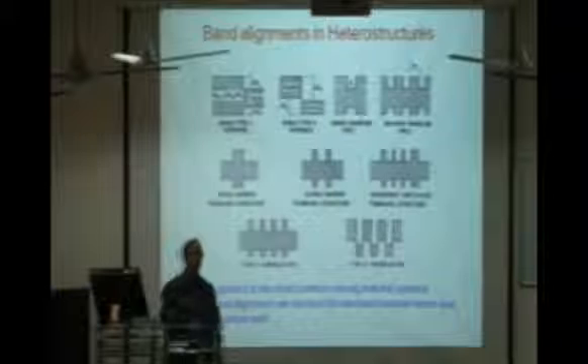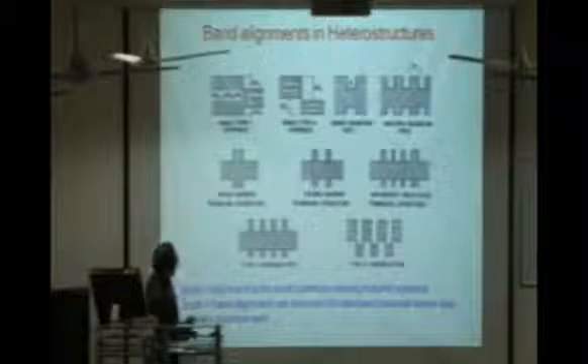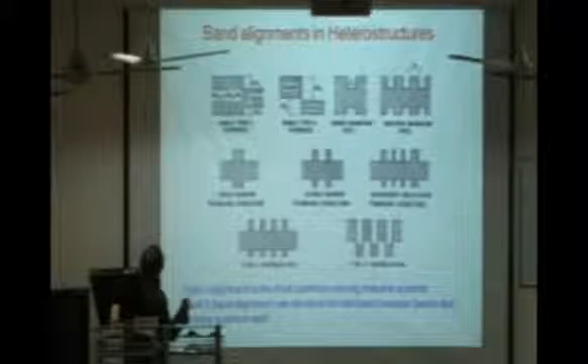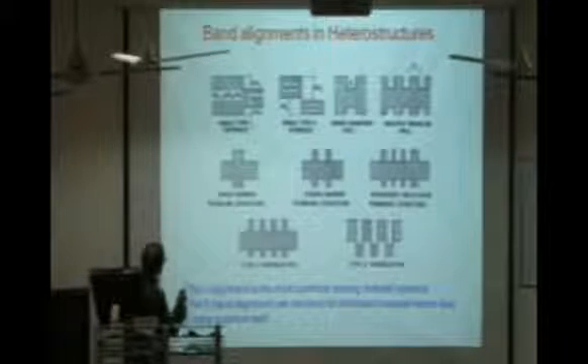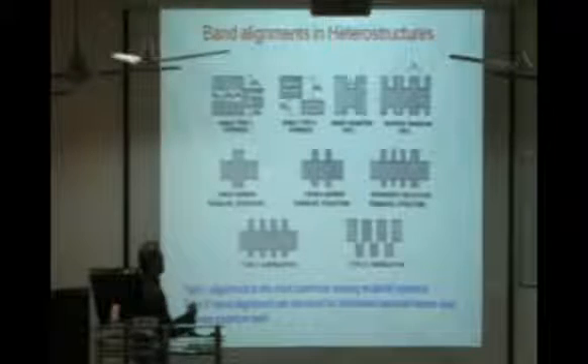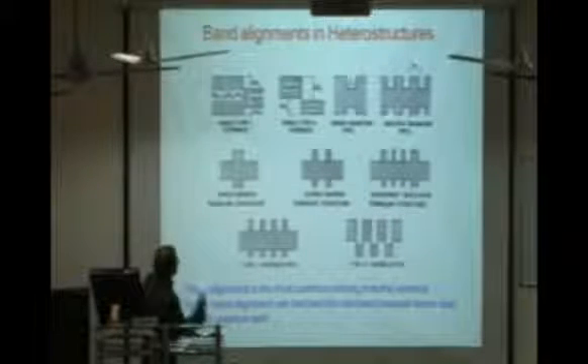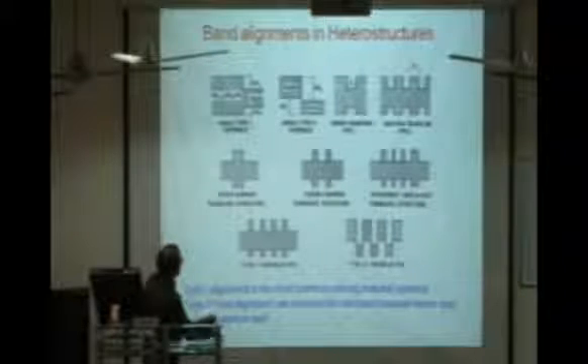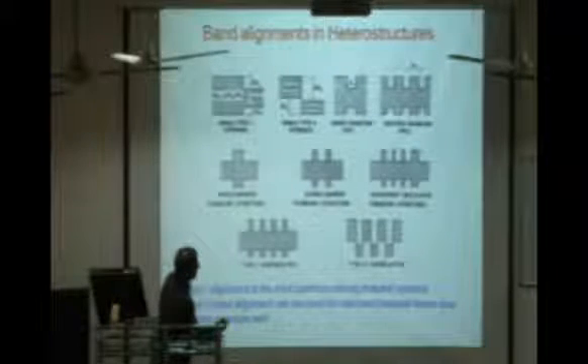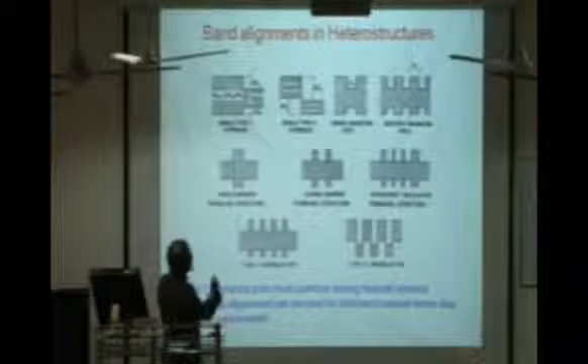In fact, there are a lot of theories, but these theories still do not really tell which combination of materials makes a type 1 or type 2. It's not a unique theory there. So in this case, as you see, we have used two different materials, indium arsenide and gallium antimonide, as one combination. As you see, this band alignment is a little bit different here. So you get a very huge conduction band offset and huge valence band offset, which is much more than the band gap difference between the two materials. So in fact, with these type 2 materials, if you just continue to make it, you can get a type 2 superlattice. And a type 2 superlattice is nothing but an example of a very deep quantum well, as you see. This is a quantum well, this is a quantum well, this is a quantum well. It's a very deep quantum well compared to the so-called type 1 alignment or type 1 superlattice.